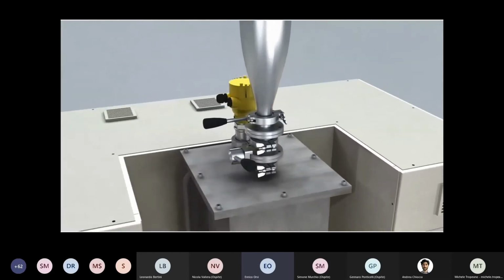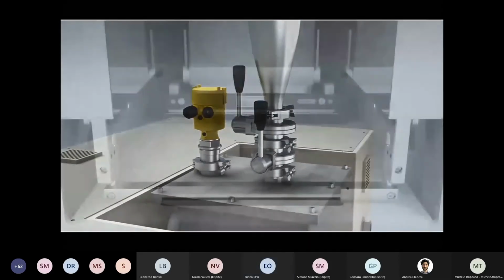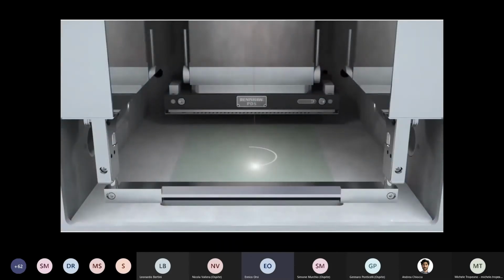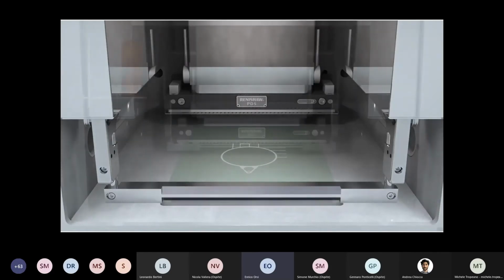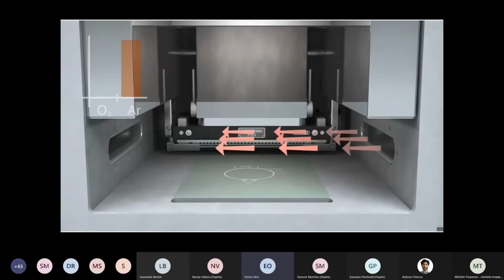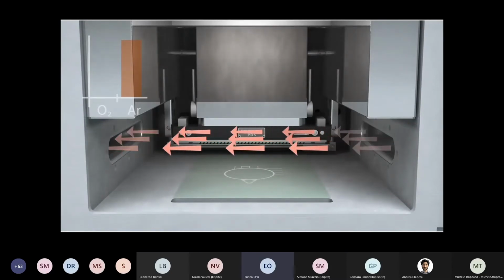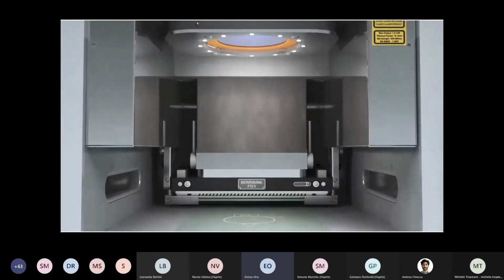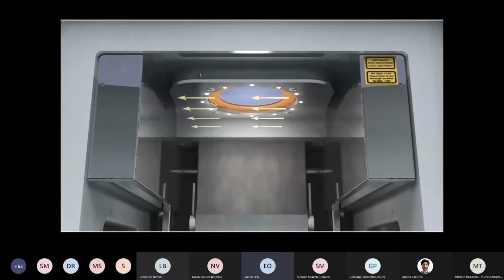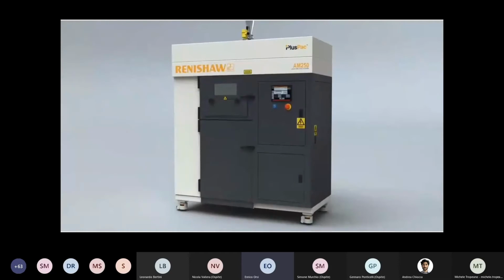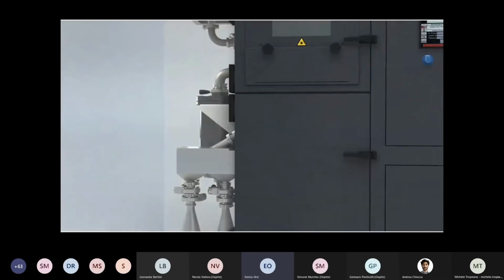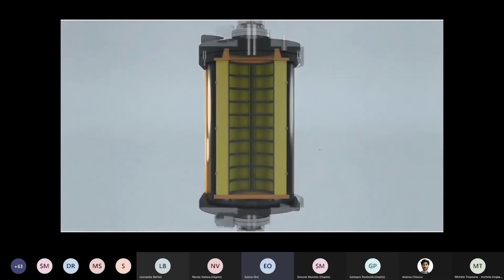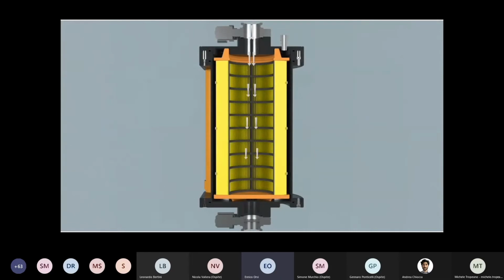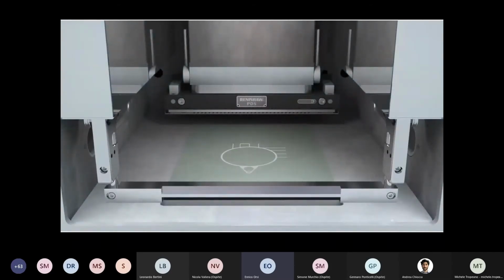So this operation is not needed anymore, and those machines are meant more for a production environment rather than for a research and development environment. As the process continues, deploying other layers of powders, we also have a very important part of the process, which is the gas flow that is continuously cleaning the process chamber from sparks and emissions coming from the process. This is essential to make sure that the laser power is deployed and reaches the powder bed in the correct way. This gas flow that contains metallic particulate is then filtered through a paper filter and recirculated in the machine.